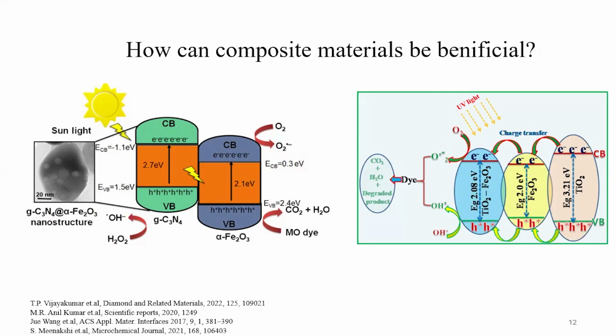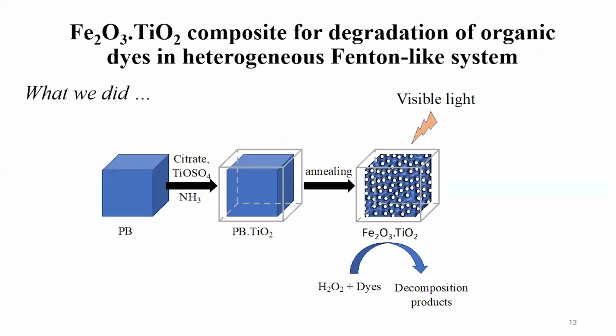However, when we couple that with other materials, for example carbon nitride or other oxides, the electronic structure of the material is changed, and it helps to limit the recombination of the electron and hole, so improving the photocatalytic performance. And in this concept, we synthesize MOF-based material from Prussian blue. We anneal that and couple that with titanium dioxide, and use this material to degrade several organic dyes in solution.